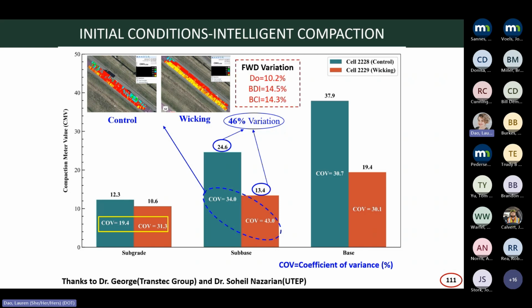In the FWD results, we see that the variation is 10 to 15%. Because the wicking geotextile is draining out the water, from that 46% variation it's lowering that variation. So it's now 10 to 15%. If we had just compared the data without considering all those initial conditions, we may say that no, this test section is not working. But when we bring in this parameter, from 46% of variation, it's brought down because of the drainage.